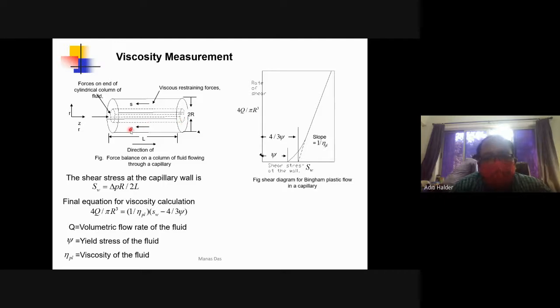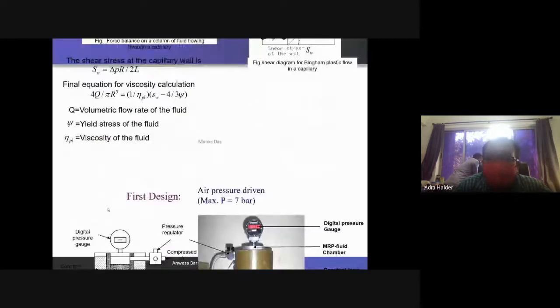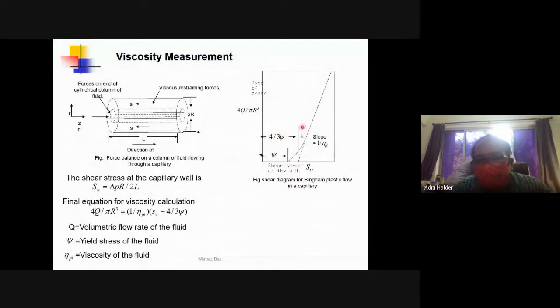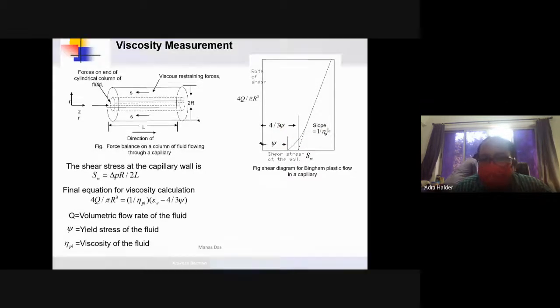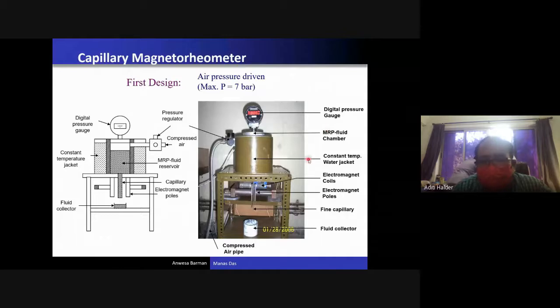The L by D ratio, where L is the length of the capillary and D is the diameter of the capillary, should be more than 40. Psi is the actual yield stress. The yield stress and this plastic viscosity are unknown, and they can be measured from the capillary rheometer experiment. At different pressures we have to measure the volumetric flow rate. From there, if you plot it, you can get the values of psi and eta PL.